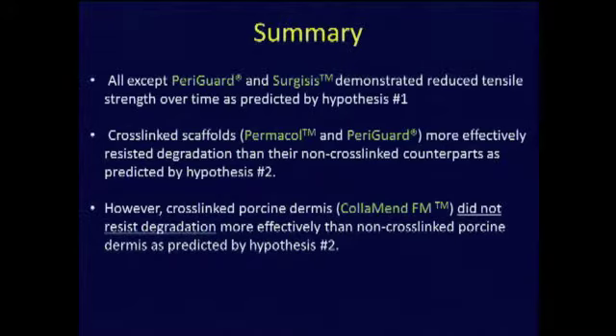So in summary, all except PeriGuard and Surgisis demonstrated reduced tensile strength over time as predicted by hypothesis 1. The cross-linked scaffolds more effectively resisted degradation than their non-cross-linked counterparts. Again, a mechanical advantage of the cross-linked materials. However, one material did not resist degradation, and this may be a result of how heavily cross-linked the material is.